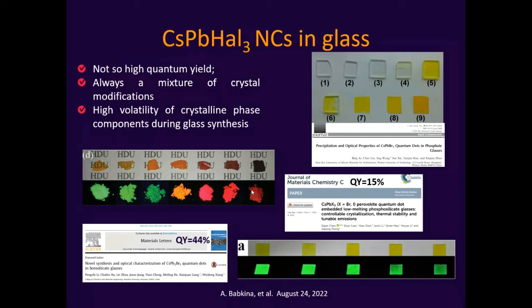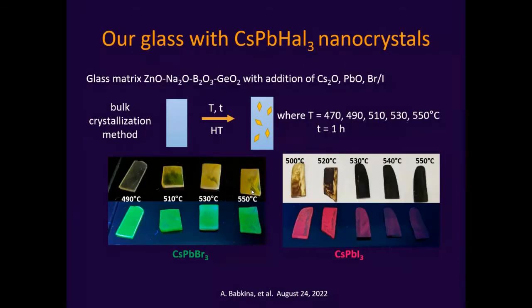But still, some papers have shown us that yes, it is possible, and you can obtain perovskite nanocrystals of different compositions inside of the glass matrix. The second peculiarity about all these papers is that they were done mostly by Chinese scientists. So we decided to take part in this race and also to synthesize glasses with the perovskite nanocrystals.